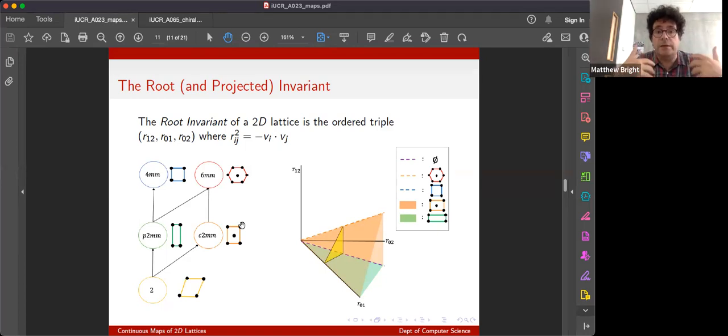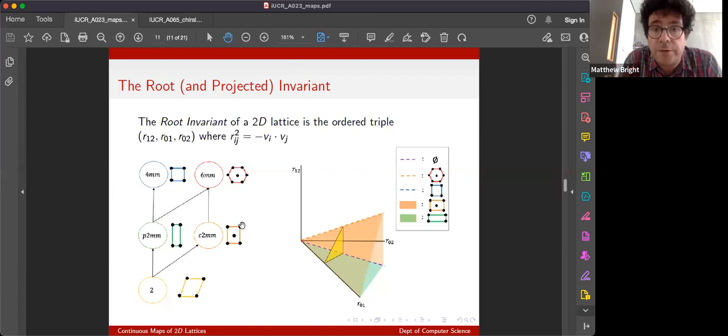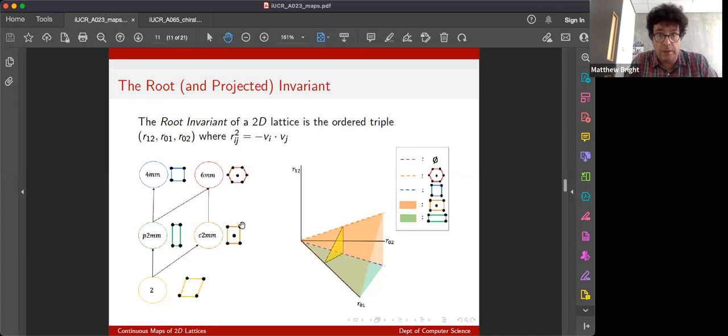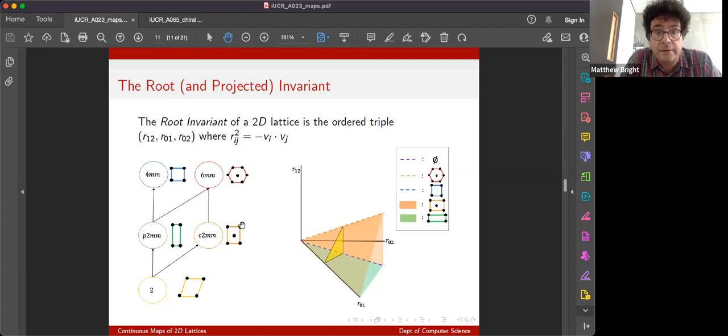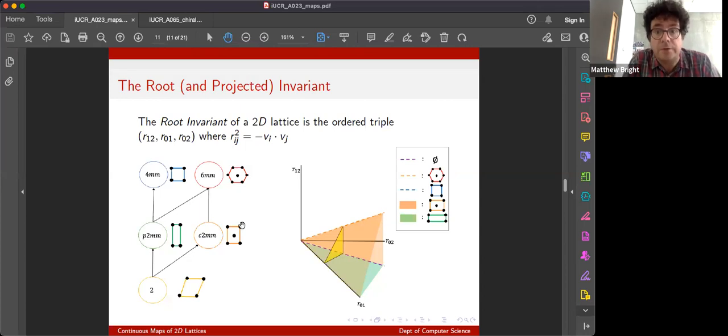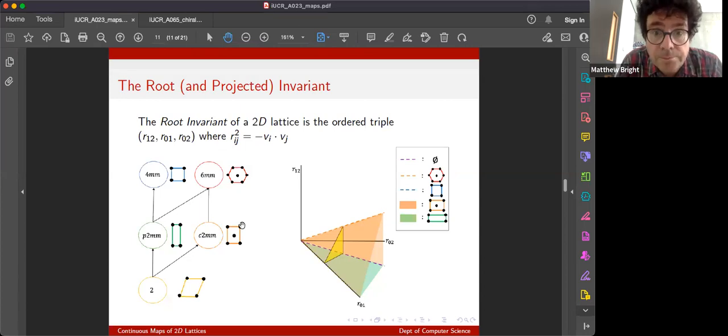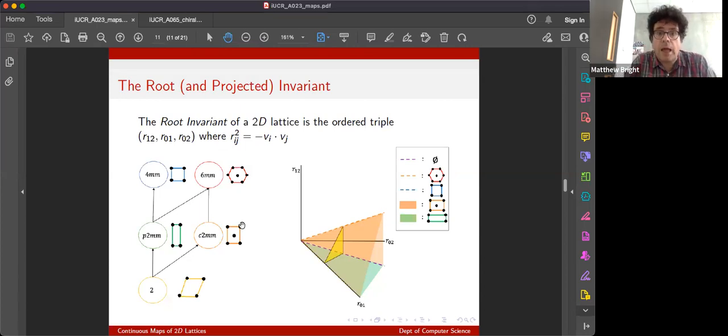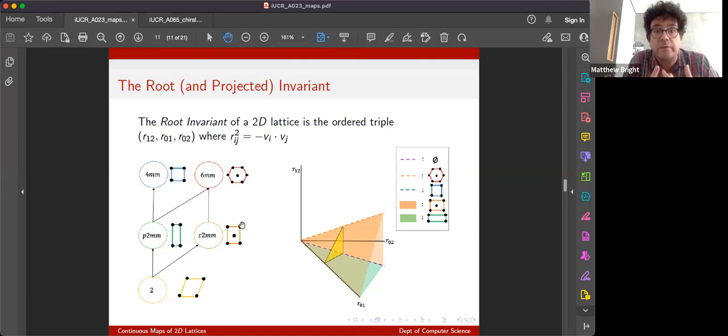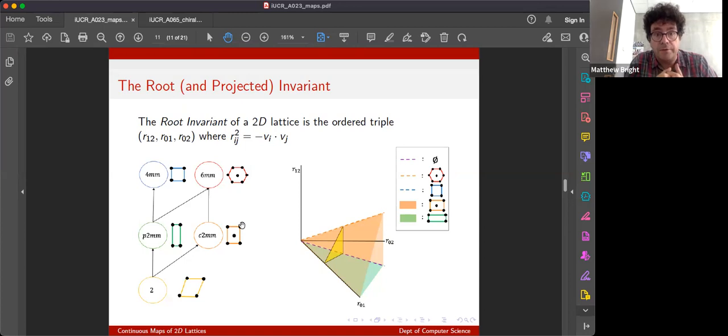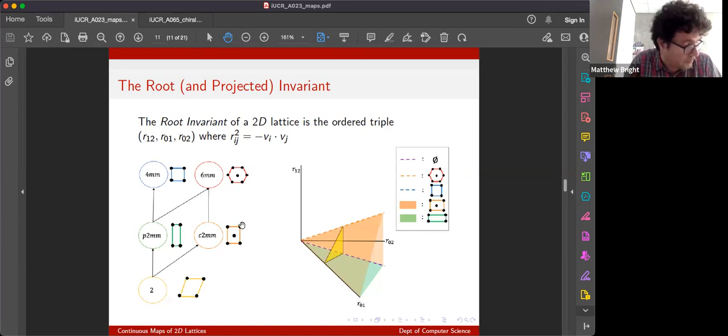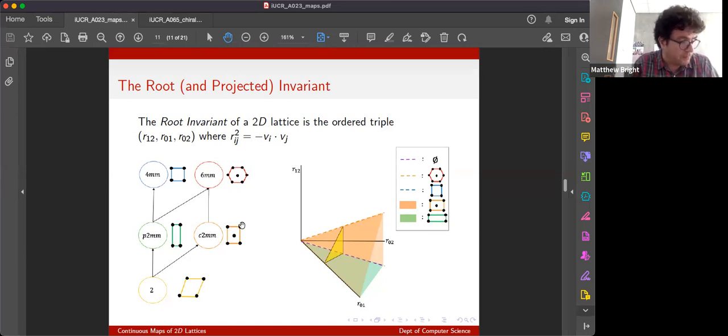And we use the square root of the inner product, or the square root of the negative inner product, since obviously if they're obtuse, the inner products are negative. So we use the square root of the negative inner product, which is a non-negative number greater than or equal to zero. And that really, the useful thing there is it means that your units of these parameters, these three parameters are the units of the lengths of the original vector. So angstroms, if you're a crystallographer, say.